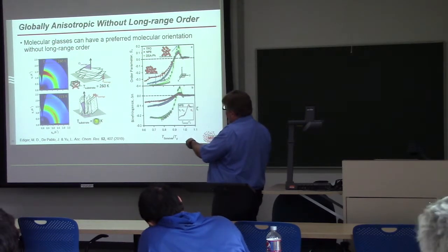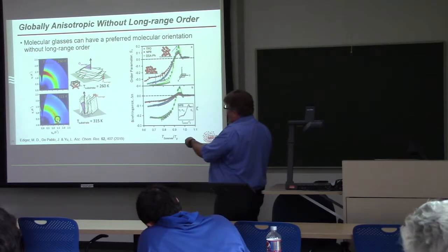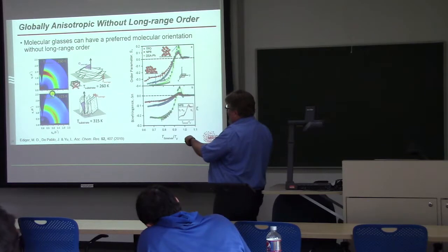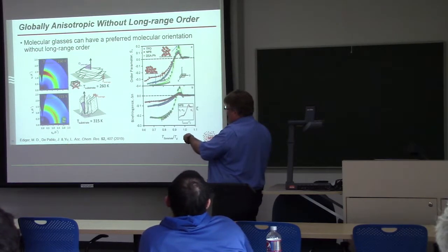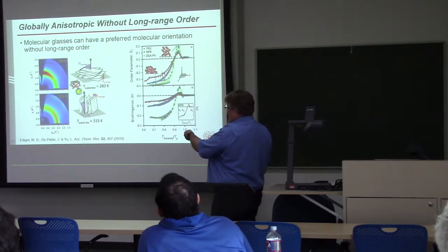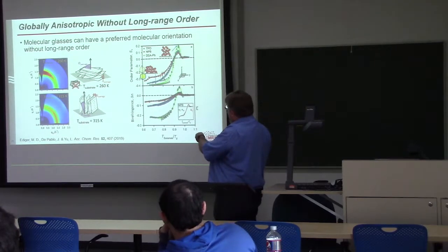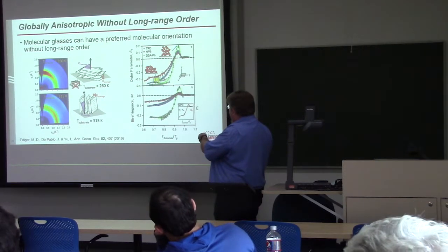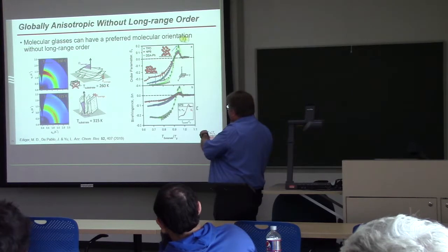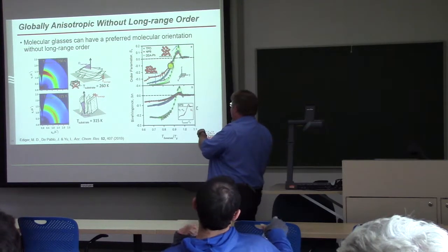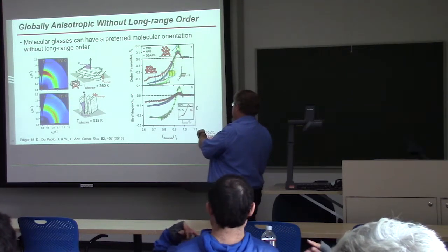And examples of a sort of rod-shaped molecule are shown here, where this is X-ray scattering data showing that the molecules mostly lie down in this class and mostly stand up in that one with respect to a substrate for the thin film growth. And here is optical birefringence data showing similar things for a different molecule and its influence on the optical properties of the resulting thin film.